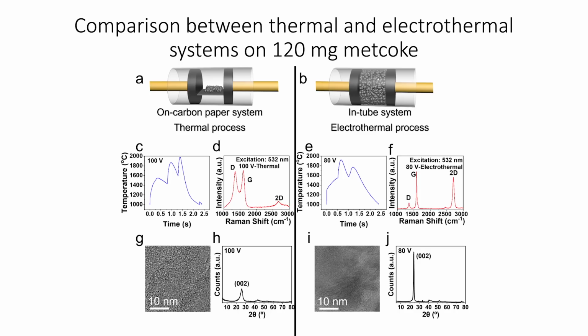One is our traditional system, where you put material between two electrodes, and we drive current through all the material. The other system is we take a carbon paper, which is conductive, and we put our material right on top of it. So most of the current is going to go through the conductive paper, not through the material sitting on top of it. Will that affect things?